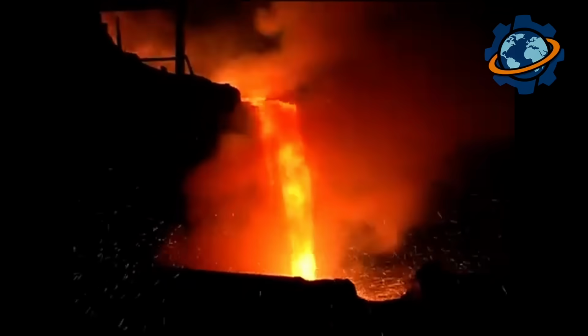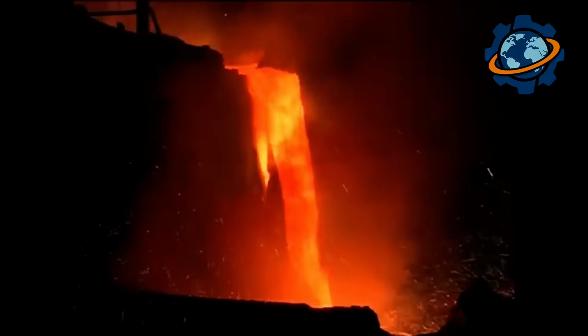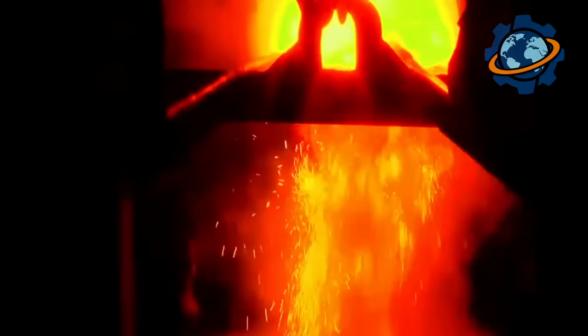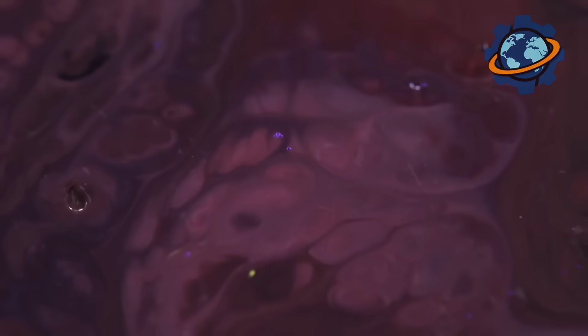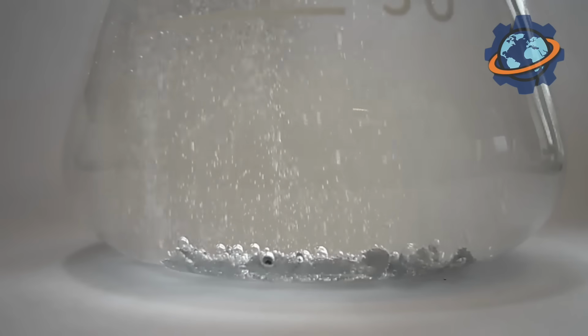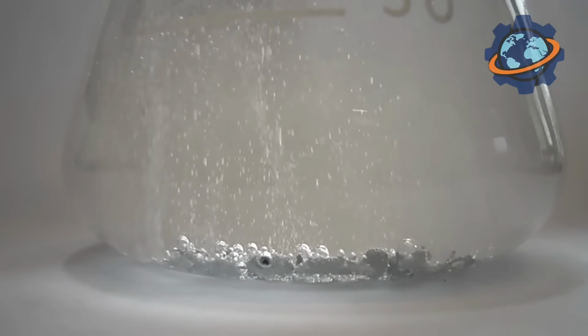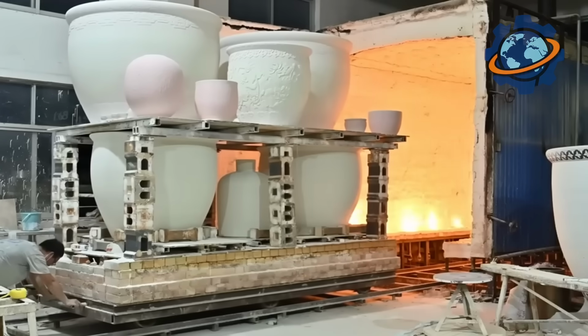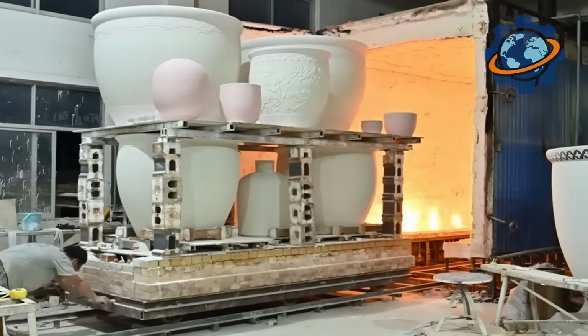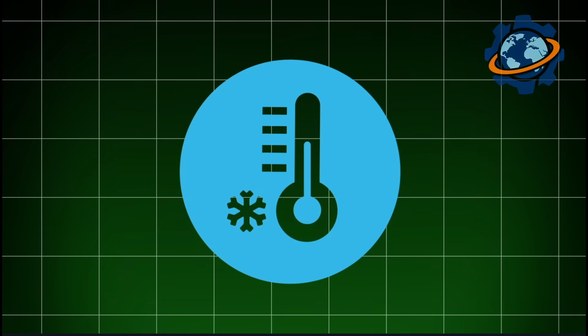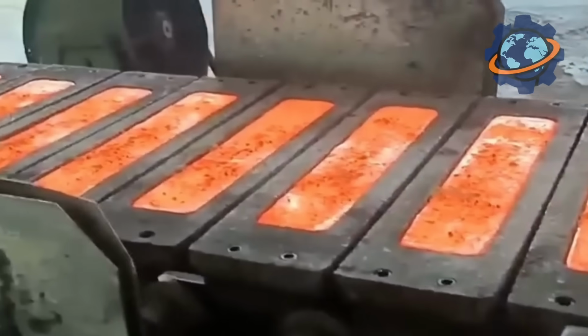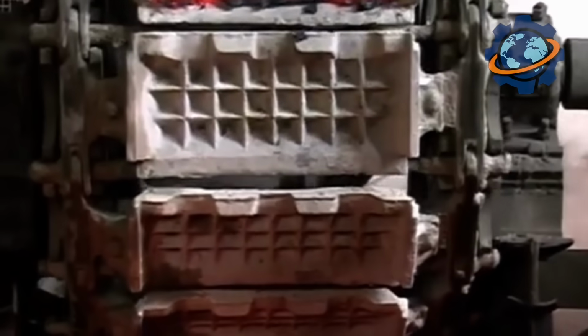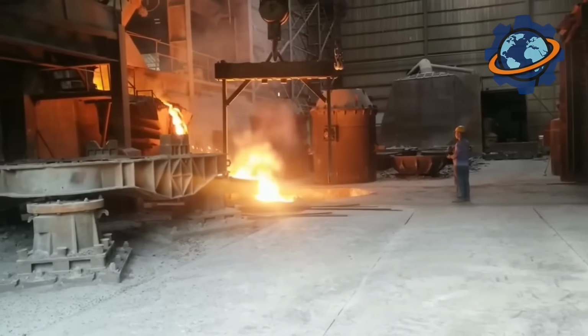At such temperatures, complex chemical reactions are triggered, mineral particles soften on the surface and sinter together, forming a strong and dense ceramic structure. In the system of aluminum oxide and silicon dioxide, new crystalline compounds are formed. In particular, needle-like crystals of mullite, which, like reinforcement, permeate the entire structure of the brick, giving it exceptional strength and thermal stability. Having passed the peak of heating, the brick just as slowly passes through the cooling zone. This stage is no less important, as rapid cooling would cause thermal shock and destroy the product that has just gained strength. At the exit of the kiln, a completely new product appears.